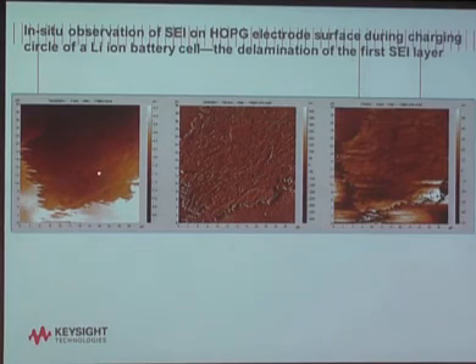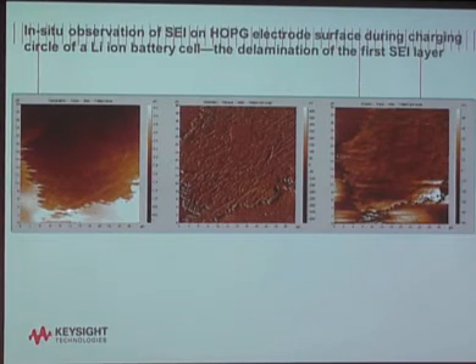And this is another example of that. We zoom out. You can see that little things. Here is the underlying layer, and there's a crust there, and then there's no obvious attachment between these two layers. As a matter of fact, in the real experiment, it's very easy for the entire thing to come off if the force is too high. So actually, it's confirmation that there are two layers of SEI formation in this experiment.